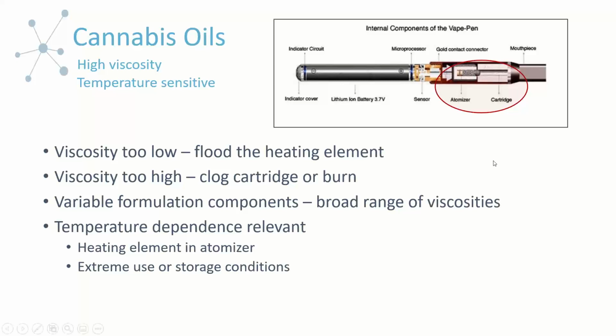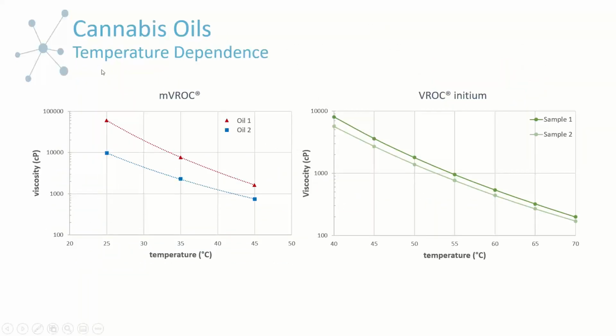So with that in mind, I just wanted to show some data so you can clearly see how different these are than some of our other products. In this particular slide, we're going to focus on temperature dependence. Both plots are viscosity versus temperature. These are just generically labeled as they were provided by a customer. They've authorized us to use them, but without acknowledging what they are. What you can see is we've measured these. These are doable on both our MVROC system and our Initium. MVROC is probably the better option because we can get to lower temperatures where we see very high viscosities.